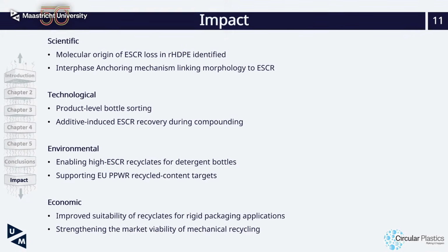This work has several impacts on several levels. Scientifically, it identifies the molecular origin of ESCR loss in recycled HDPE. It introduces a new mechanism that can describe additive-induced improvements in ESCR, linking morphology to crack resistance. It paves the way to design next-generation additives targeting this property.